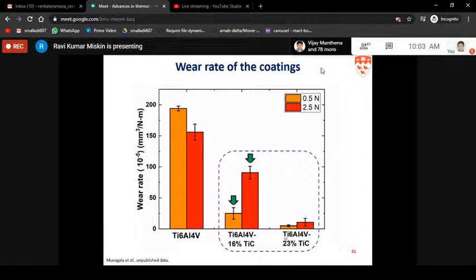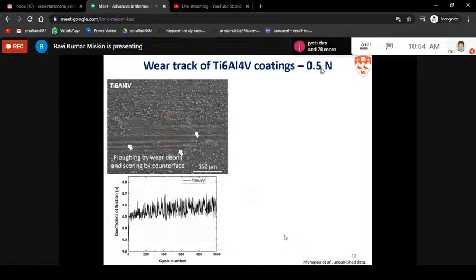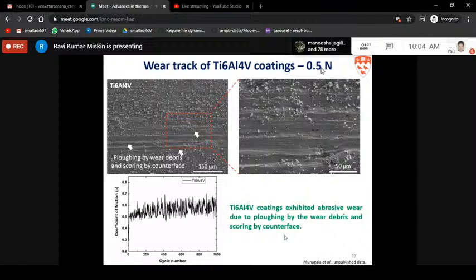Yeah, so this is basically the comparison I'm showing, that is 16%. There's a slight increase in wear rate at 2.5, which we'll see why next. But for our 23% coating, the wear rate is extremely low. So you can see that even if you increase load, there's a very marginal increase in your wear rate. Next, once we have the result, the next step is to understand the science behind why we are getting this.